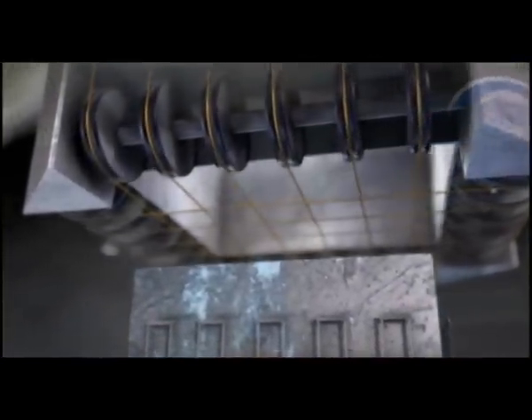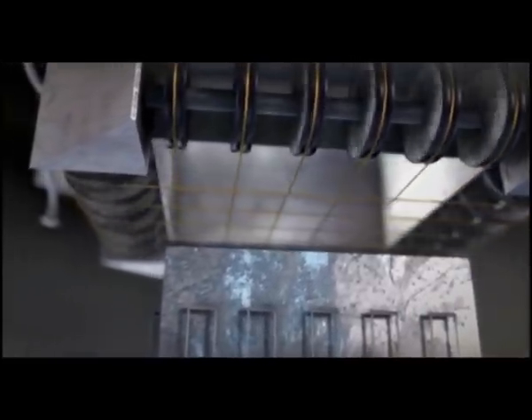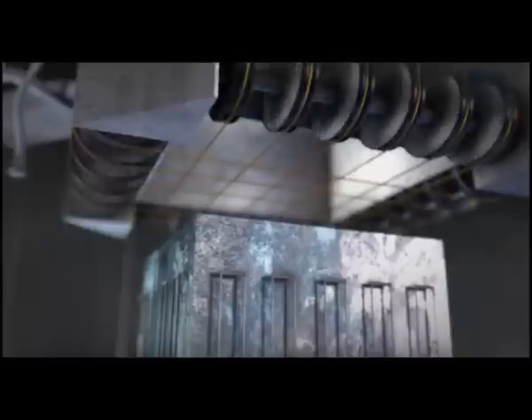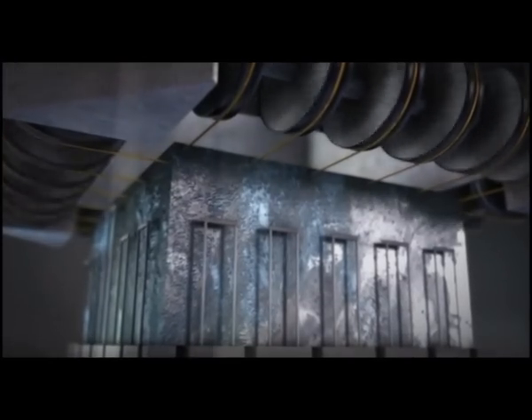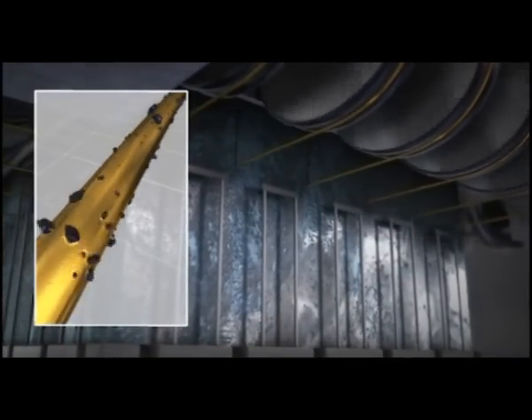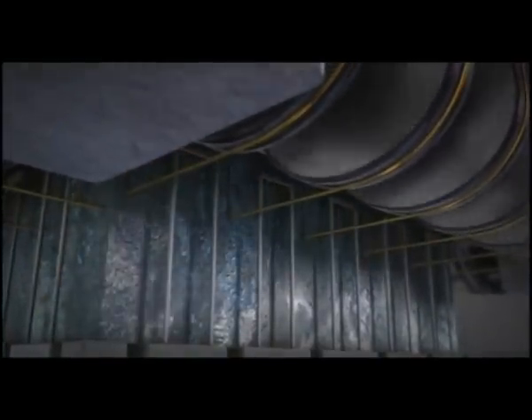A view inside the briqueter shows a cutting head with numerous deflection rollers, over which a special wire runs. The arrangement of the rollers ensures that the wire saw produces a matrix corresponding to the cross-section of the bricks. The cutting head slowly sinks downwards, causing the wire saw to cut through the silicon ingot. With rapid to and fro movements, the slurry, which consists of a mixture of silicon carbide and polyethylene glycol specially developed for the silicon cutting process, is kept in motion.